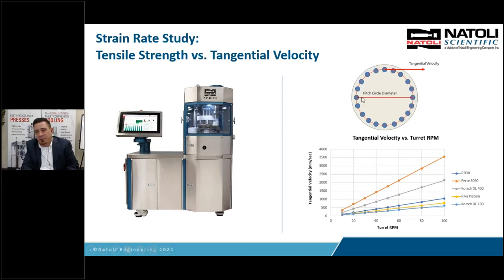That is called your pitch circle diameter. If you know that, you know the RPM times pi divided by 60 gives you millimeters per second, gives you a velocity. Now I can run my RD30 at 50 RPM, which is probably equivalent to about 500 millimeters per second. Now run my big production press at 500 millimeters per second. Now you're speaking apples to apples. You should expect similar results.